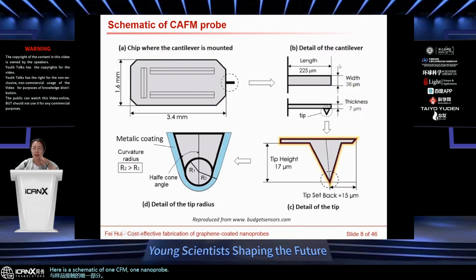And we know that the length and the thickness of this cantilever determine the frequency or the spring constant of each nanoprobe. Before we start one experiment, we need to consider which type of nanoprobe we want to use to get reliable or high resolution information, but we do not want to damage the sample. For C-AFM nanoprobes, there is a metallic coating, which is around 20 to 50 nanometers. And the tip radius is very important because it determines the quality or the resolution of the images.